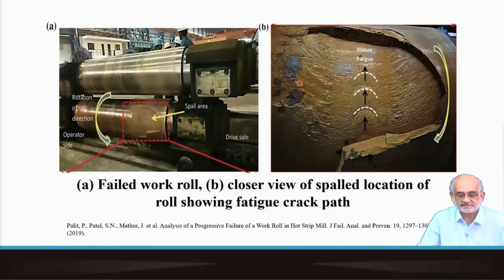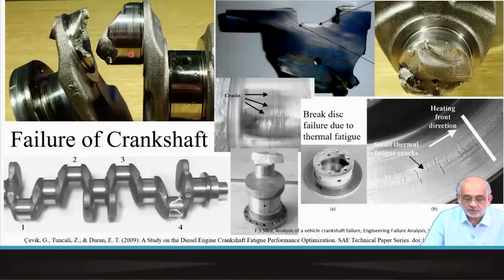So we would like to certainly arrest this, and this is very important, not just in a roll, but look at this failed crankshaft. You know very well that these kinds of crankshafts are very useful for transmitting dynamic motion or load from one end to the other. And as you can see, the various parts of the shaft, 1, 2, 3, 4, not all of them underwent the failure or developed such a crack. But here you can easily see at point number 4, there is already a crack which has been detected by a dye penetration or non-destructive evaluation process. And if it continues to be used, then certainly this part will crack and will separate.